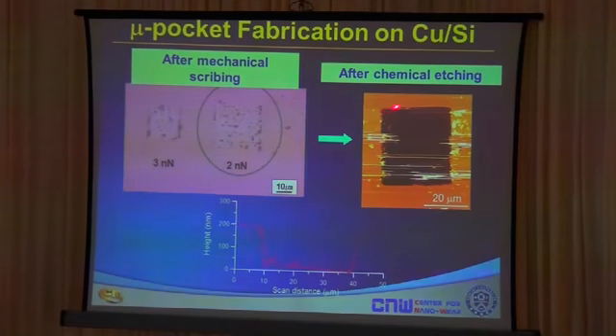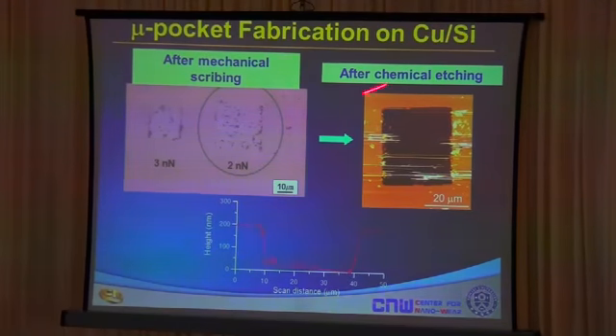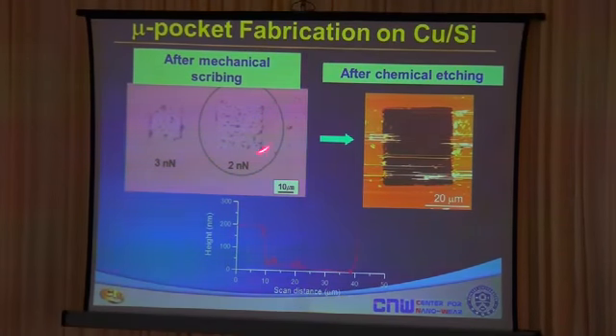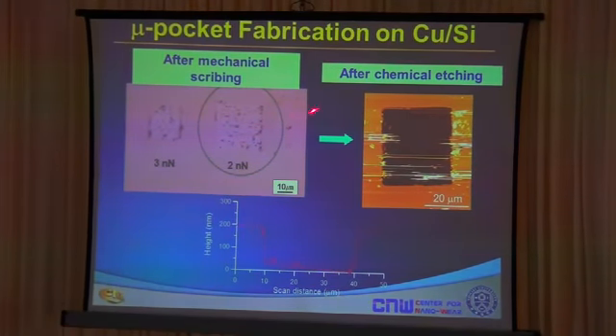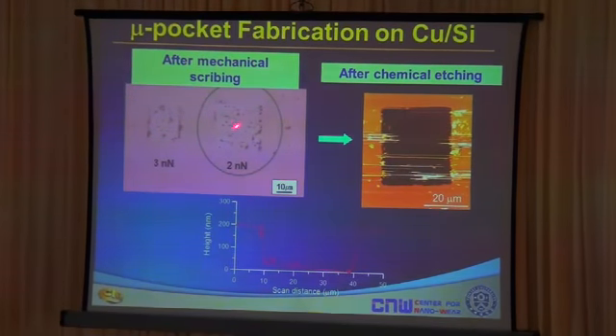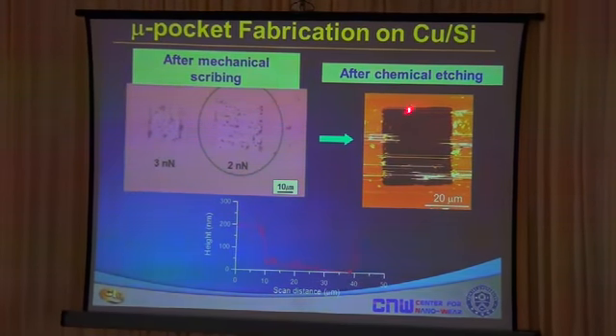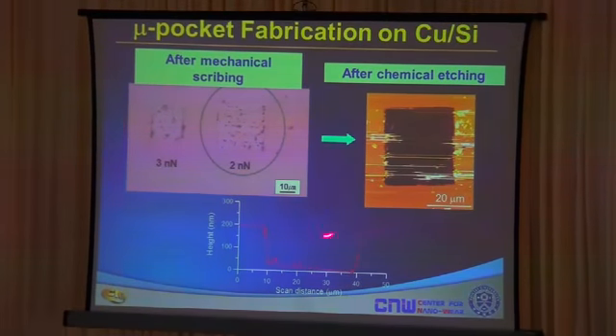And we can also make pockets on a copper surface, which has been coated on silicon. This would be the kind of pattern you get after mechanical scribing with 3 nanonewtons force, and this would be 2 nanonewtons force. So after mechanical scribing, you do not see the pattern. But if you etch the surface, you will now expose the surface to create this kind of pocket, which is about 200 nanometers in depth.